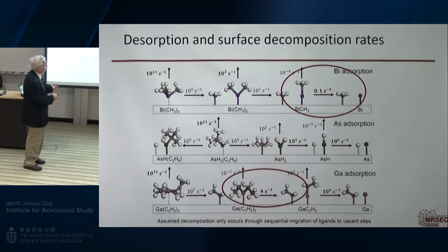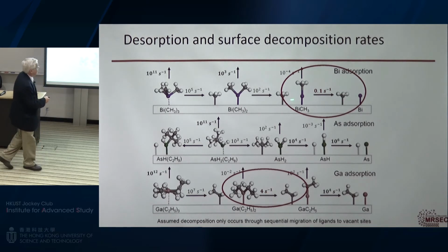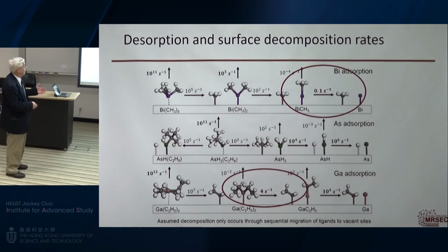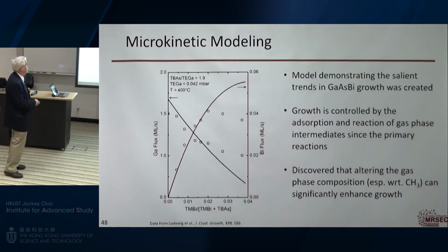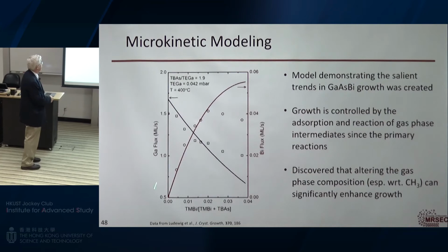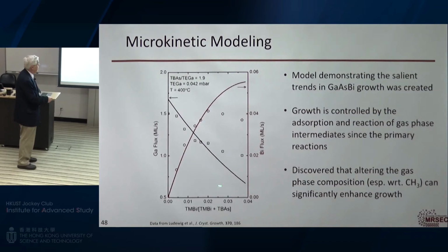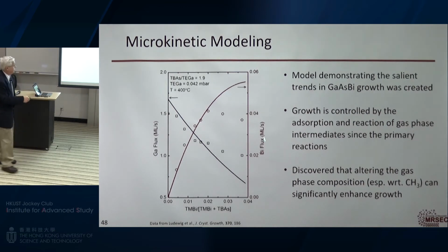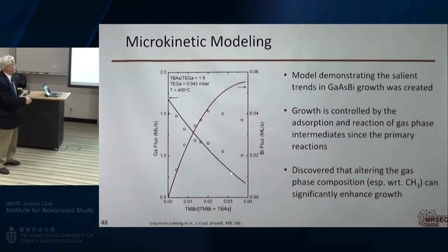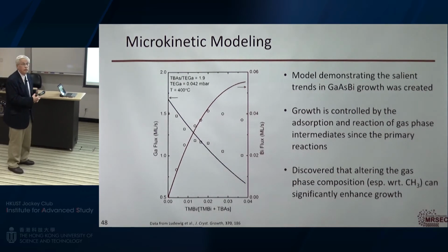So we can use chemical means and selective adsorption on the surface to stabilize the surface and prevent phase separation, and hence create a new alloy. So we took all those reactions and put them into a combined microkinetic model that asked, can we predict, as a function of the various parameters, and this is growth data from the literature, the various compositions of bismuth and the growth rate of the material? And you find out that you can actually compute to a large degree many of these things.